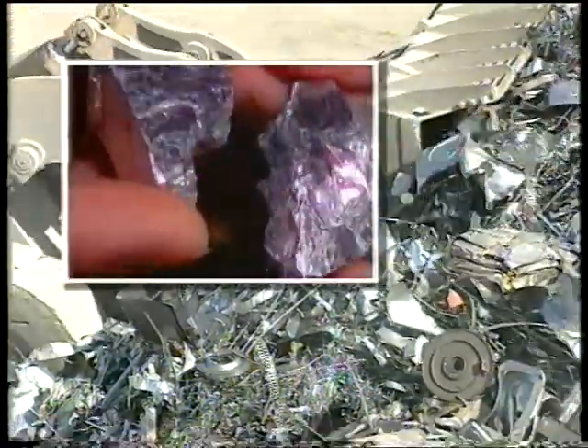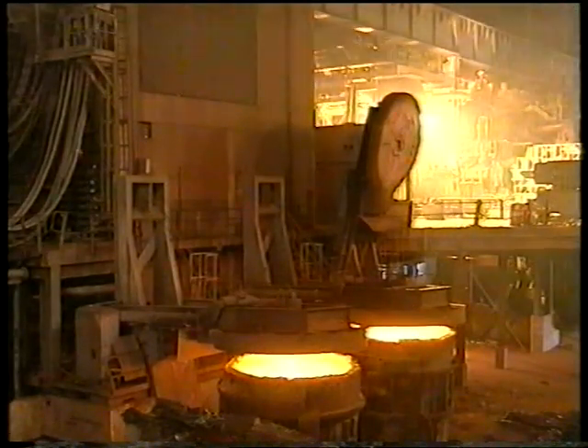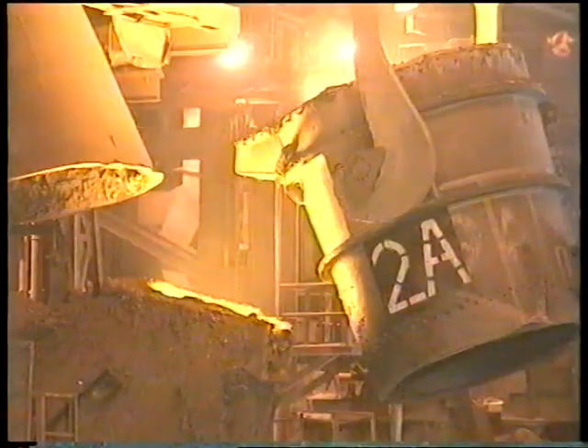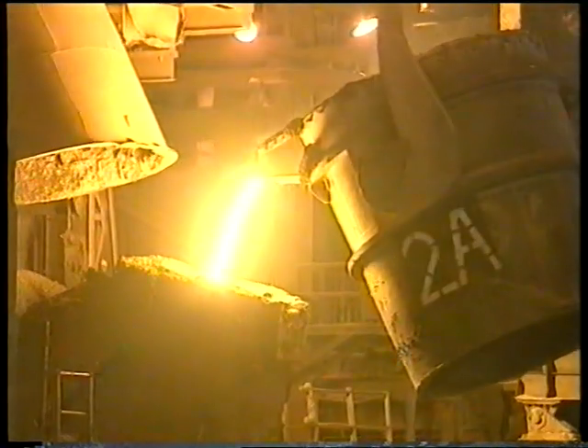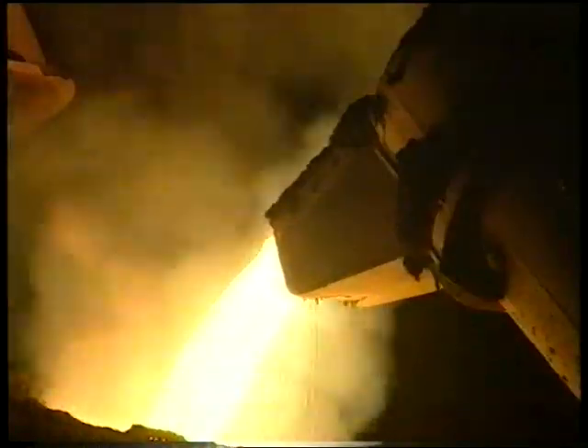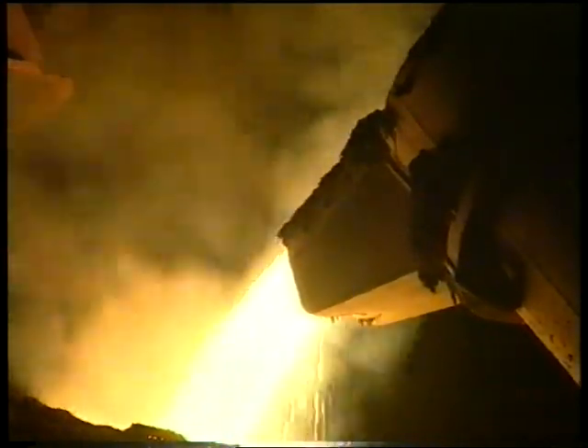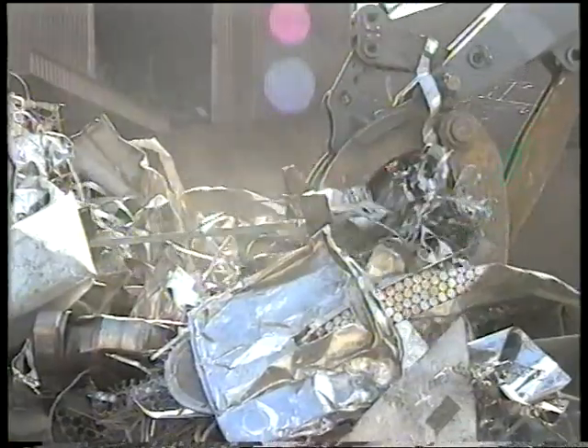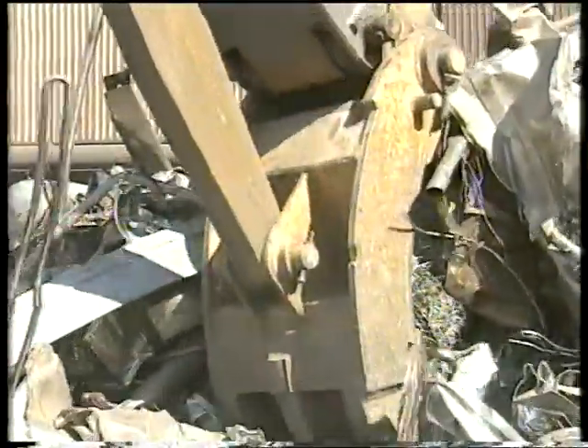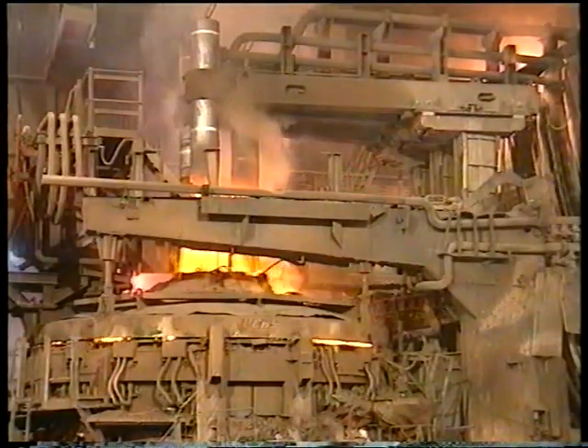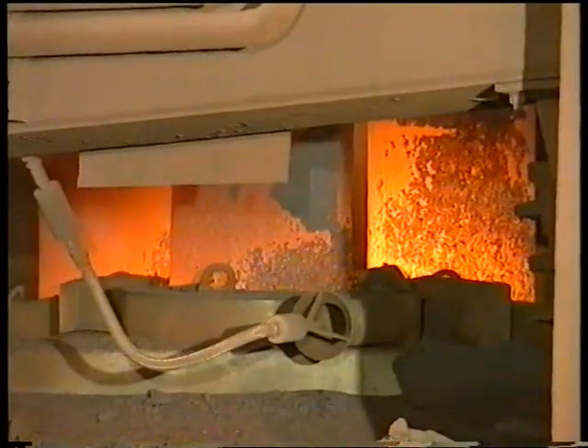The first stage in the stainless steel manufacturing process involves the melting and casting of a combination of raw materials. The stainless melting and continuous casting plant, known as SMACC, is capable of producing 600,000 tons of steel annually and is one of the largest and most efficient stainless melting facilities in the world. Production is based on recycling high-grade stainless steel scrap, which is mixed with ferroalloys. First, the scrap is melted in the electric arc furnace. It takes approximately 90 minutes to melt 130 tons at a temperature in excess of 1650 degrees centigrade.